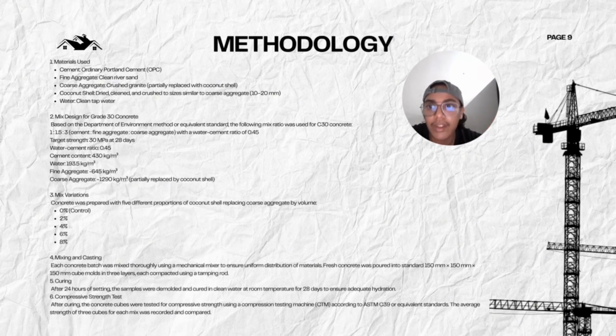So for our mix variations, the concrete was prepared with 5 different proportions of coconut shells replacing the coarse aggregate by volume. The first is 0%, which is the control, and then 2%, 4%, 6%, and also 8%. And for mixing and casting, each concrete batch was mixed thoroughly using a mechanical mixer to ensure uniform distribution of materials. Fresh concrete was poured into standard 150 millimeters by 150 millimeters by 150 millimeters cube molds in 3 layers, each compacted using a tamping rod.